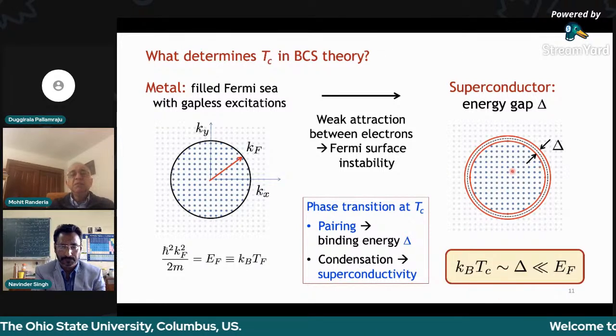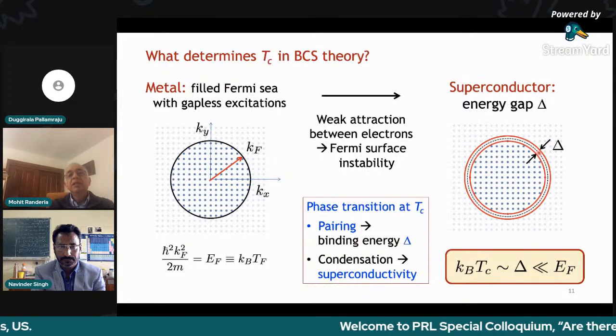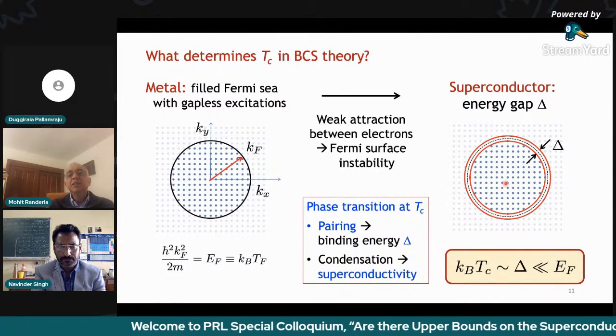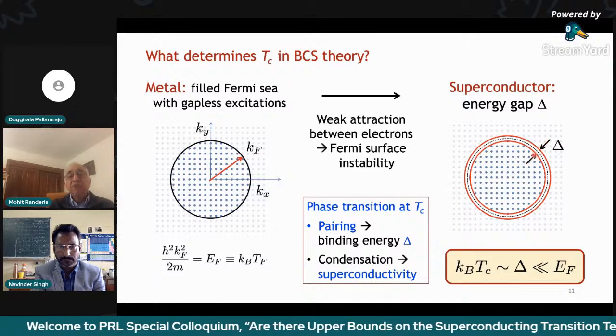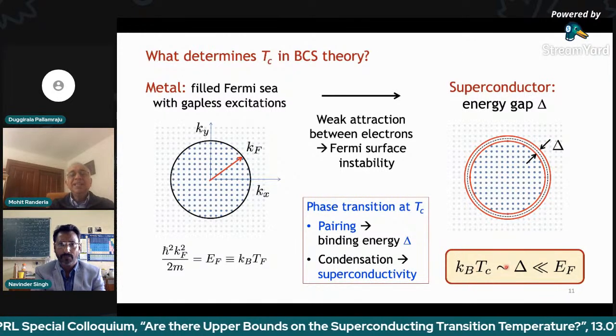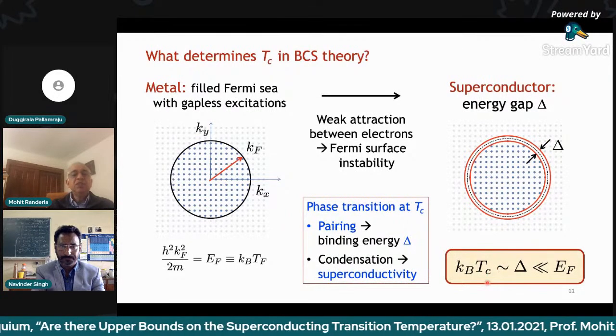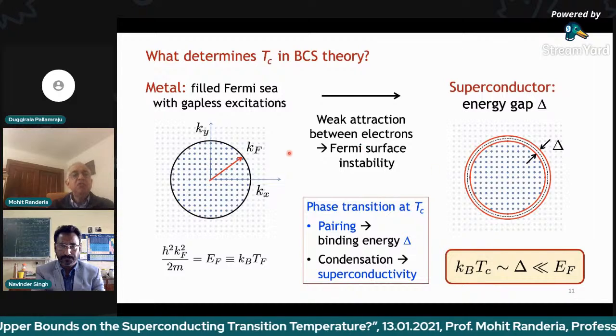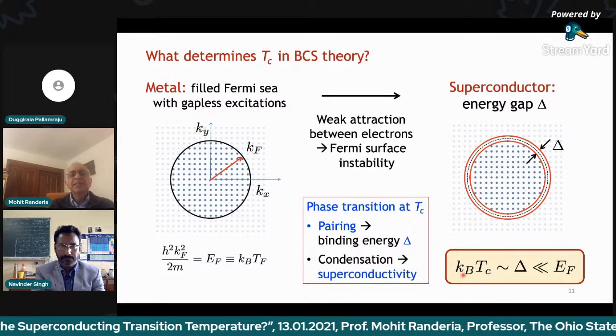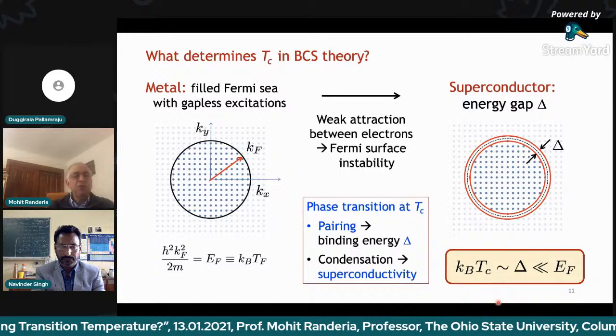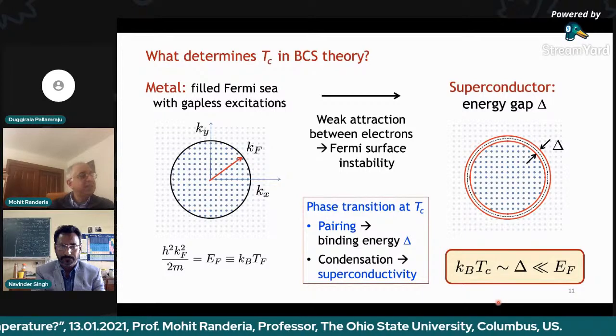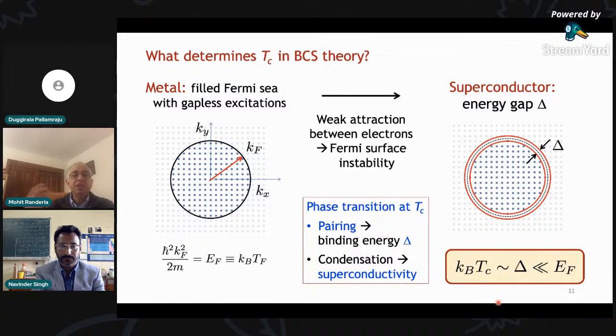So you can see from this picture, since you have a very weak attraction, the binding energy is very small. So delta in the energy scale is much, much smaller than the Fermi energy scale. So TC, the transition temperature at which superconductivity is destroyed and you go back to a normal metal, scales with delta. There is some standard formula, 2 delta over kBTC is 3.5. The number is not important, but the larger the energy gap, the larger the TC. The two are proportional to each other.